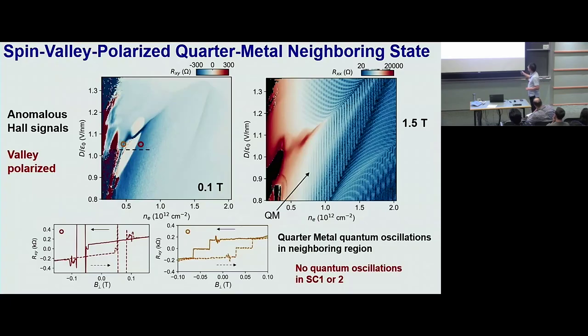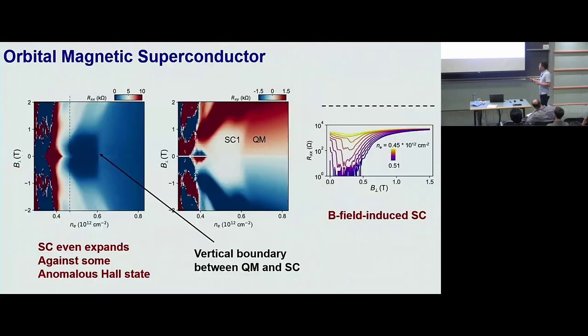So given that you know the neighboring state to the superconductivity, at least SC1, is a spin and valley polarized quantum metal, you can ask, can I use that as a probe to tell what's going on inside the superconducting state? The logic is very simple, okay? Spin and valley polarized quantum metal has outer plane orbital magnetization. When you apply an outer plane magnetic field, you can lower the energy of that quantum metal. If the superconductor is not magnetic or not as magnetic as the quantum metal, then the phase boundary between the superconductor and the quantum metal is gonna move towards the superconductor and convert part of it to be quantum metal.